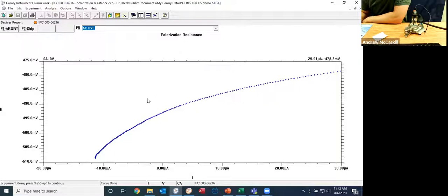You want to take data relative to this OCP value that we're looking at, because the RP value you're looking for is just a way for you to get that I-corr value. You cannot measure I-corr directly. There's no technique to do that. Some people would say, well, if you're measuring the open circuit potential, there's no current flowing right there, shouldn't I-corr be 0 amps?